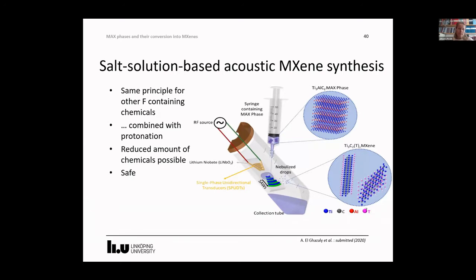What is important is that the process uses only salt, lithium fluoride, and water, which eliminates the use of harmful acids or bases. It's safe to handle because the solution only temporarily attains a pH value between 4 and 5 when the surface acoustic waves are used, and then it recovers to a value above 6 within minutes after we've stopped the surface acoustic waves.